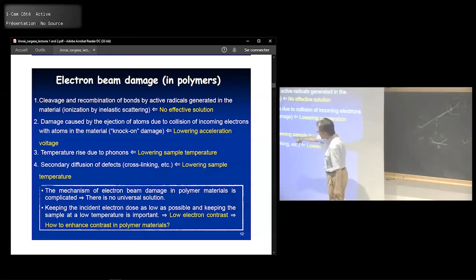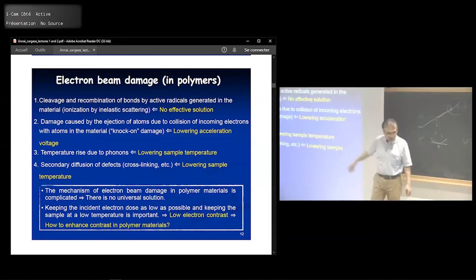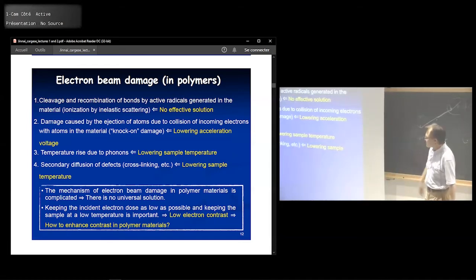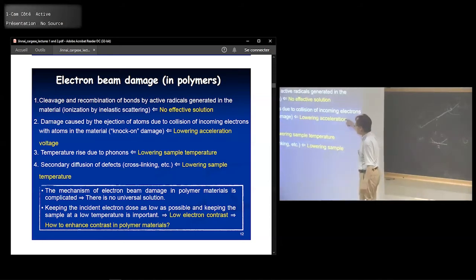Another thing is secondary diffusion of defects, like cross-linking. It's related to the first one. When you irradiate the beam, the radical forms, and sometimes the radical attacks the double bonds, for example, and then it takes a chemical reaction. Sometimes it's the cross-linking. So it's closely related to this. Lowering the sample temperature might help in this case. So from these damages, what you can learn is that lowering the acceleration voltage and lowering the sample temperature would help.